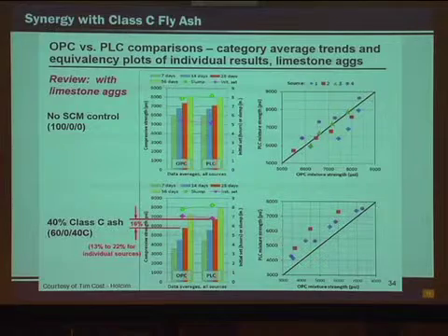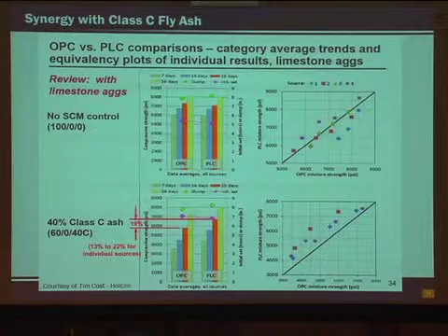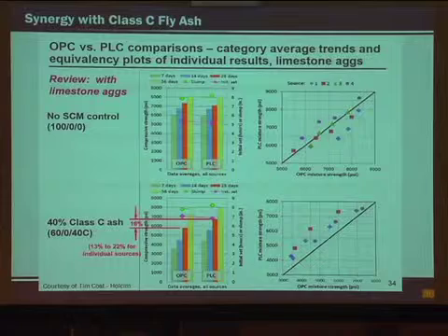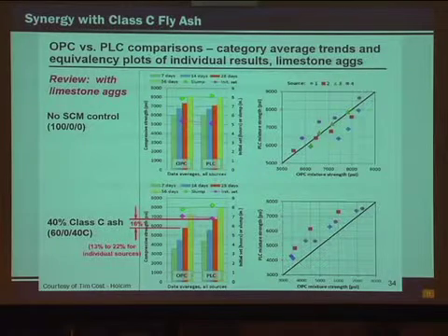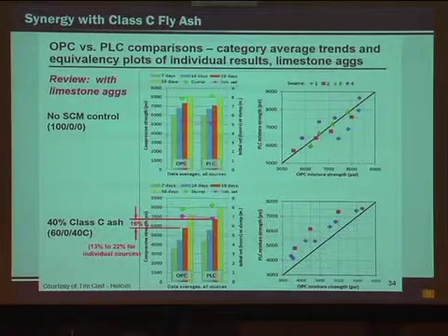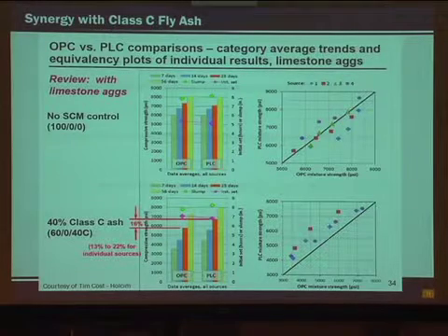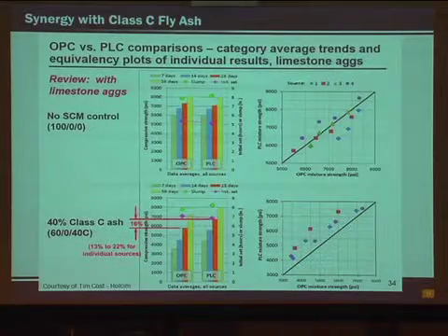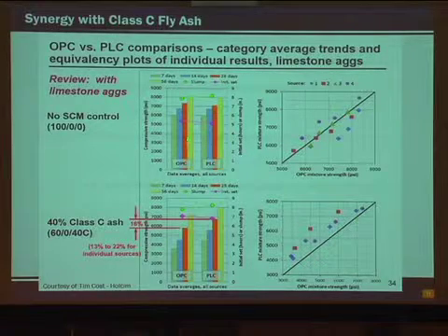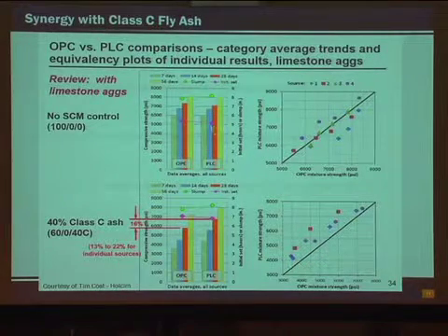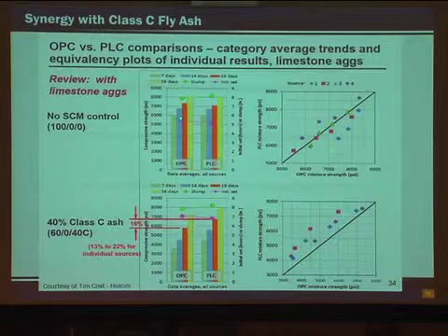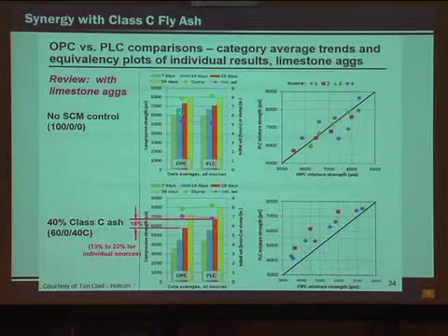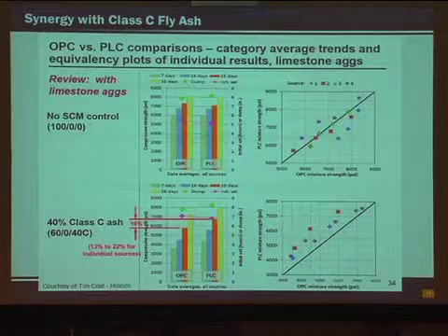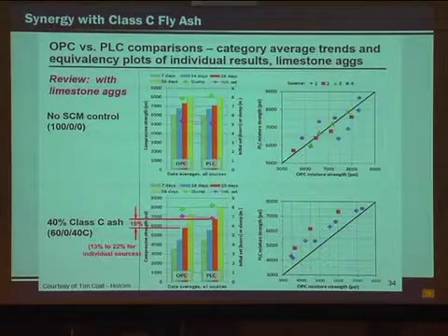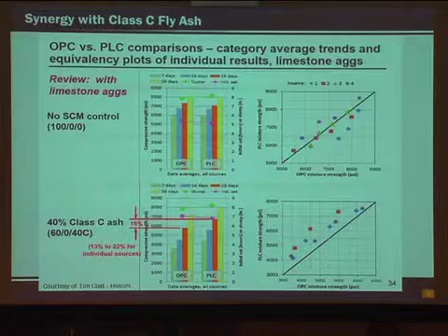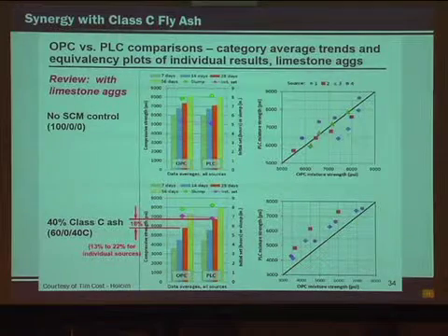All right, one of the bigger things that people are finding is this strong synergy between type 1 cements and class C fly ash. And so this is with a limestone aggregate. This is an ordinary Portland cement, and this is a PLC. So just looking at the two, again, as I showed before, there's very little strength difference between the two cements. If you look at the 1-to-1 plot here, they're basically lining up right along that line.